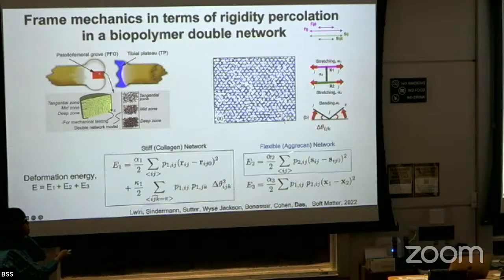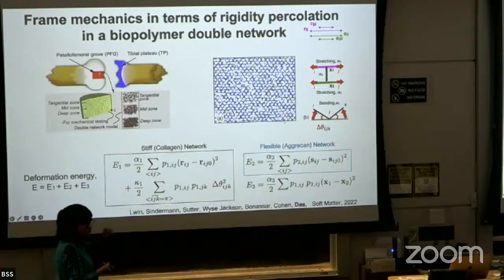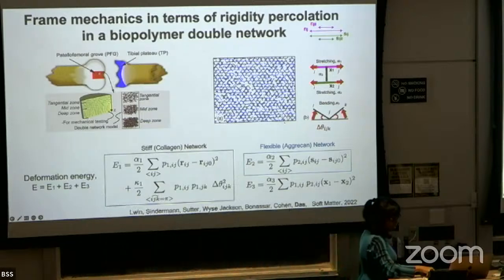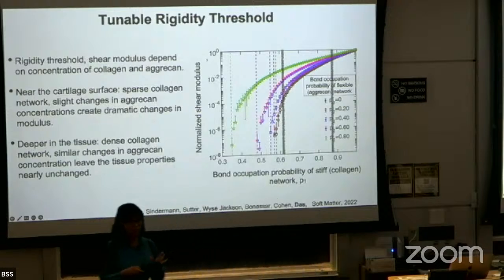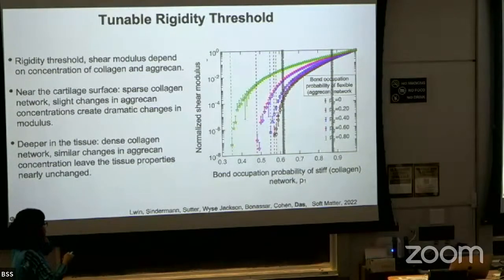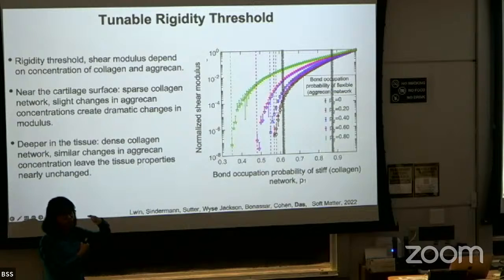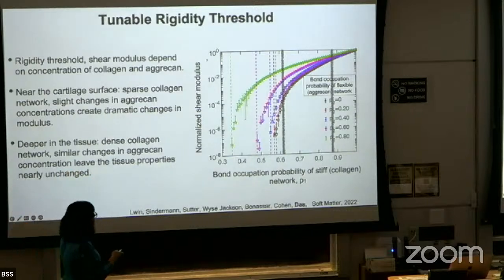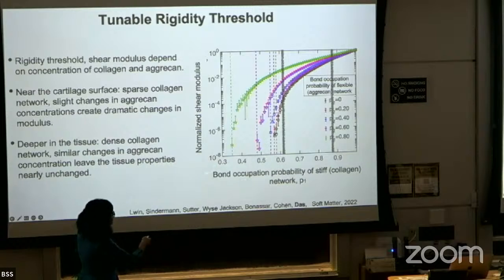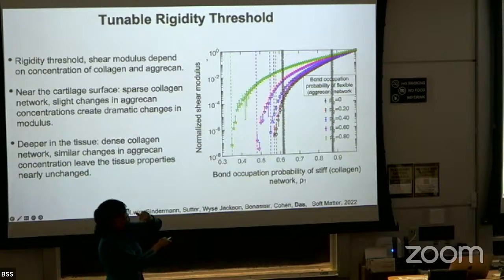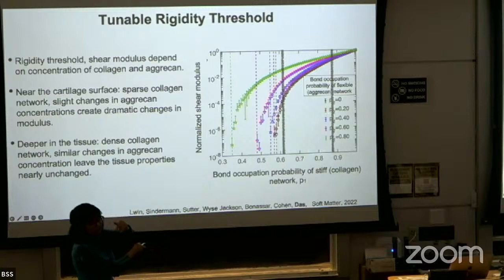Now, I could have also had this flexible network be semi-flexible or stiff, but for cartilage-specific things, the aggregate hyaluronic acid secondary network is more flexible, so we drop the bending part. Before we do anything else with this network, we wanted to look at the percolation threshold and the shear modulus. Once again, we only apply a small shear deformation, and then we look at the normalized shear modulus. Normalized means it's normalized by the value where the network is completely ordered, where all the bonds are present. Along the x-axis, I'm varying the occupation probability of bonds in the stiff network. For the legends, it is the occupation probability of bonds in the flexible network.